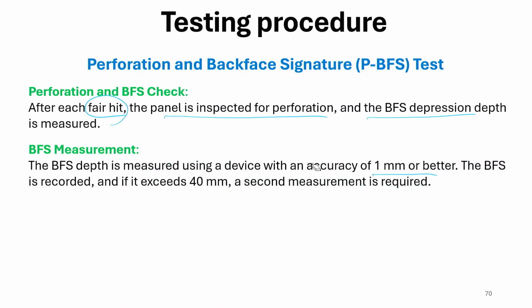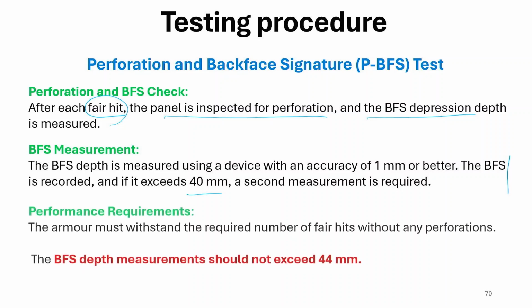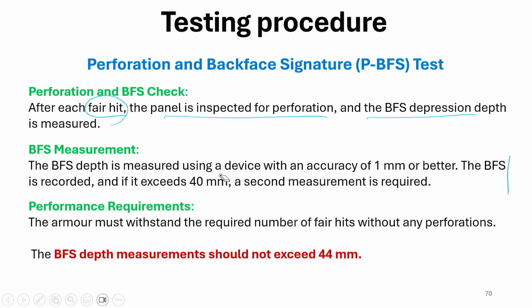Suppose the back face signature is suddenly going high. If it is more than 40 millimeter, we have to recheck. It may be due to the actual body armor, or maybe something wrong with the leveling of the backing material, or with the gripping and placing of the body armor. So, there may be some doubt, so we have to retest if it exceeds 40 millimeter. And the perforation requirement is that the armor must withstand the required number of fair hits without any perforation, okay. And the back face signature depth measured should not exceed 44 millimeter.